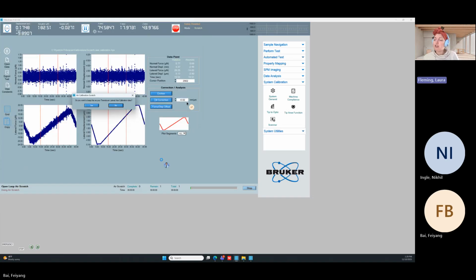Now we also get our first view of the scratch analysis screen. In this screen, you get 4 graphs. Let's go clockwise. You get normal force, normal displacement, lateral force, and lateral displacement. Now keep in mind we had programmed the normal force and the lateral displacement. So my first thing I always do for every scratch, whether it's a Cal Air scratch or any standard one, is: did it do what I asked it to do? And what I asked it to do was have 0 force in the normal direction. And then I asked it to move back 5, forward 10, and then back 5. So did it do both of those things? It did.